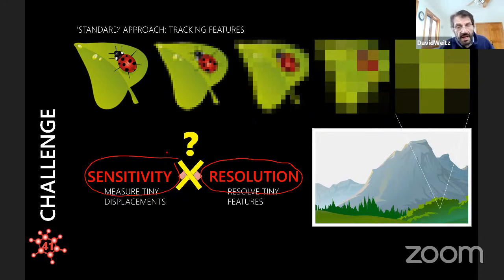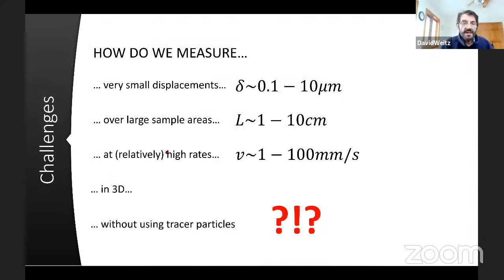And so what Stefano did was he came up with something that can measure very, very small displacements, really submicron, tens of nanometers, over very, very large areas, centimeters, and at relatively high rates, and in 3 dimensions, in all directions of motion. And he came up with the technique, and I'm going to describe that now, that he calls dynamic speckle holography, DSH.